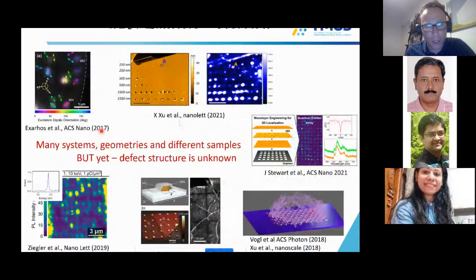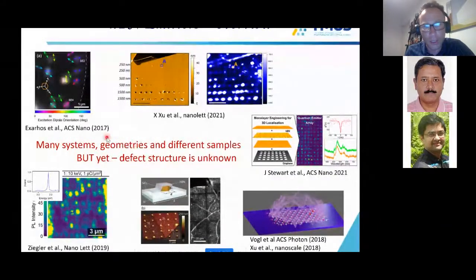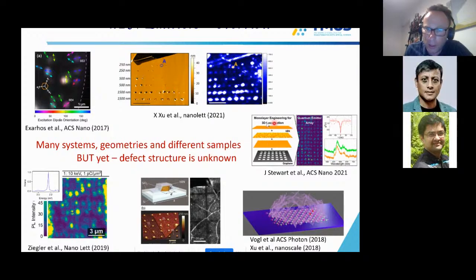Okay, so as I mentioned, quite a few groups actually started to study these materials, this hexagonal boron nitride. And the beauty of it is that you can really engineer these emitters in many different ways by positioning hBN on pillars and doing plasma processes and implanting. And very recently, also indenting with an AFM tip. And one very interesting work here is from the group of Stefan Hoffman.